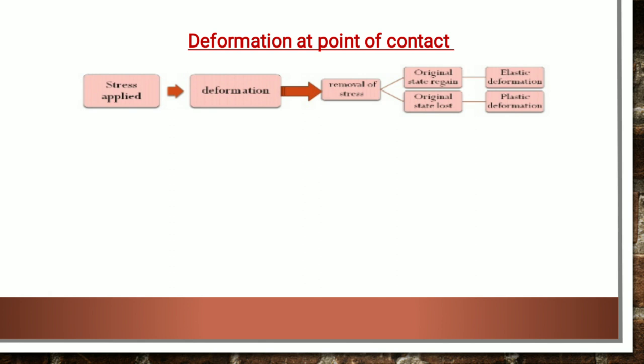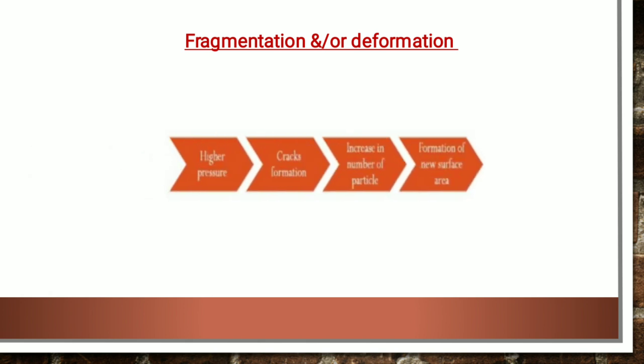Here you can see fragmentation and/or deformation. At higher pressure, fractures occur when stress within the particles becomes great enough to propagate cracks. Fragmentation causes further densification by infiltration of smaller fragments into the void space. With some materials, fragmentation doesn't occur because the stress is released by plastic deformation. Plastic deformation may be through a change in particle shape or sliding of groups of particles in an attempt to release the stress, which we call viscoplastic flow.